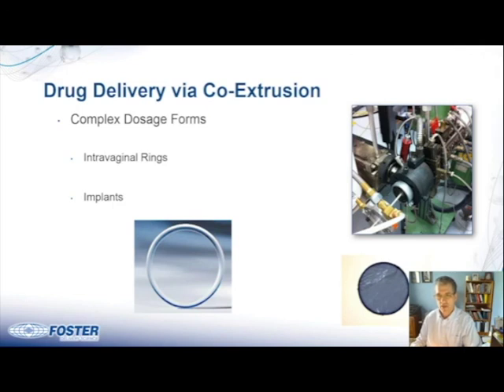In this case, we have a single screw shown on the top right, feeding into a co-extrusion head, and on the left is a twin screw. And in this case, we have a drug-loaded core with a rate-controlling membrane. Here you can see a cross section, and we used a black colorant just to show the concentricity of the drug polymer matrix in the core, and the black membrane on the outside. This is about 4.5 millimeters in diameter, and this skin layer is about 0.1 millimeters.